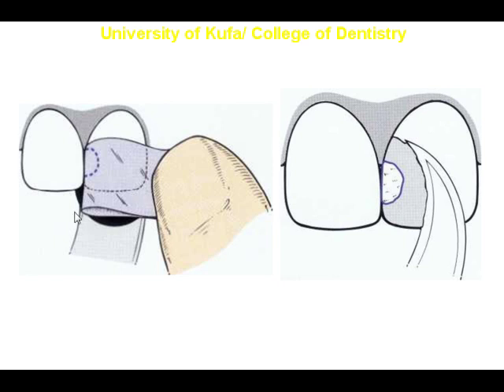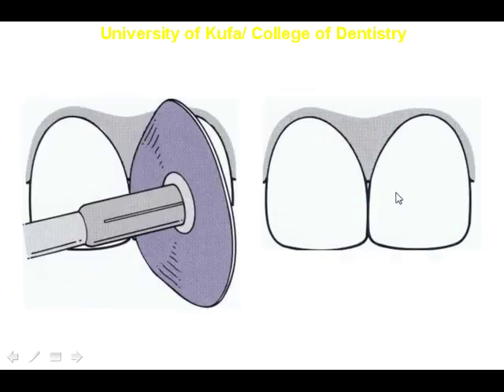We use our fingers to pull the celluloid strip before applying the light cure. This is done to pull all the composite inside the cavity, pulling the fillers present inside the composite and letting some of the matrix — the fluid of the composite — resurface on the filling surface, giving the filling a very glossy and smooth appearance. Then we light cure it. We can also use the light cure device from the palatal aspect to cure that side of the filling. After that, we bring a sharp instrument such as a blade and scrape away any excess cured material, then use polishing burs or polishing discs to remove any excess and smoothen out the composite filling.